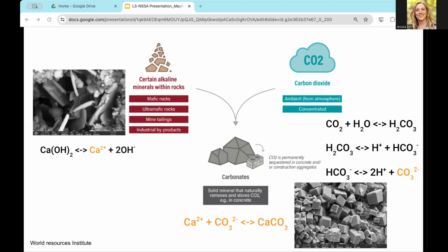Cement is a really complex material, but there is a material called calcium hydroxide, and people call it portlandite. Once it is dissolved, it produces a calcium ion and two hydroxyl ions. So the hydroxyl ion increases pH, and we have a source of cations there. If you look at the SEM image, I think it was a 64,000 times zoomed-in image of the cement surface, you can see that hexagonal plate there, and that's portlandite. This is a reactive species in the cement.